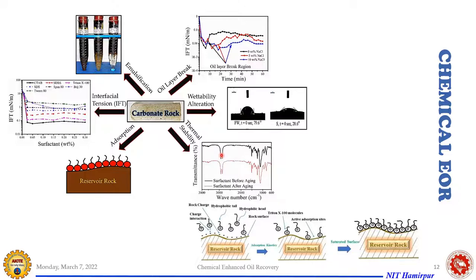There are two different approaches which I have used to identify the thermal stability. First, I have taken the surfactant and gone through TG analysis, that is thermogravimetric analysis. It shows at what temperature the surfactant mass goes on decreasing. I haven't shown the data here, but we have found that up to 200 degrees centigrade the chemicals are stable and do not degrade, considering the chemicals that we have screened through this analysis. Since the chemical will be in the reservoir for certain months, we take the surfactant, age it at different temperatures for a certain number of days, and then we take it out before aging and after aging, and send it for different characterizations.